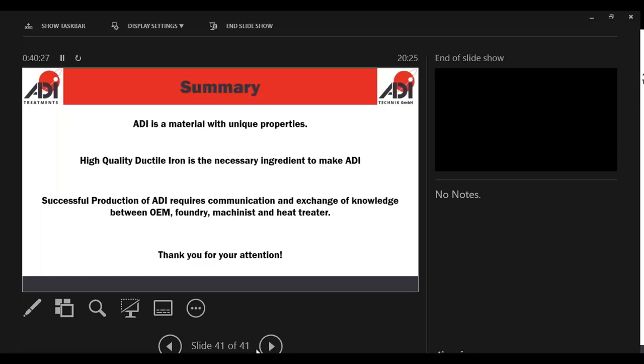We talk about getting the properties the same in all sections. It may not be necessary. It may only be necessary to austemper a few millimetres or the surface of the structure, because when you look at large components, it's only the surface where the high stresses are. So you might be able to austemper even a 200 millimetre thick section, just use something with very minimal alloying to get the surface transformed, to get the ADI transformation of the surface.